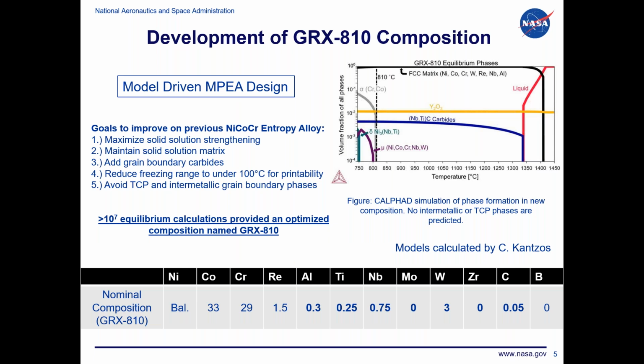So we initially started our ODS alloy development work looking at a base alloy composition of nickel, cobalt, chrome, and equal atomic metals. There had been some literature that showed promising results with nickel, cobalt, chrome, and it was very printable. So it was a great composition to do a foundational study with. But at elevated temperatures, there really isn't anything that special about nickel, cobalt, chrome. And so what we wanted to do was take that base alloy composition and add other elements to try to improve the high temperature properties of this alloy. And so we set 5 goals here.